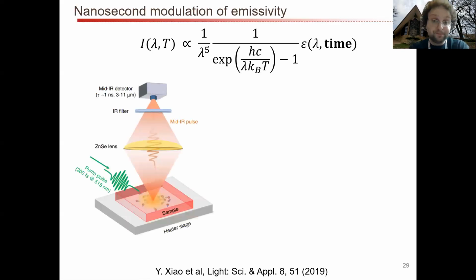And so what we wanted to do in this work, which was published in Light: Science and Applications in 2019, was to demonstrate the fastest ever modulation of thermal emissivity. The way that we did this is we took some semiconductors, we tested silicon, gallium arsenide. Here I'll show you the gallium arsenide result. It's just a wafer of gallium arsenide, nothing fancy. Undoped gallium arsenide usually has a very low emissivity because it's reasonably transparent in the mid-infrared.